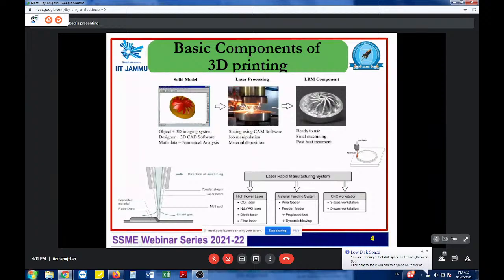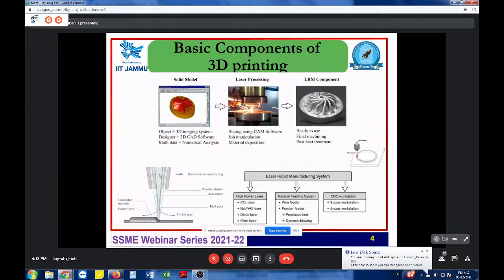The final ready-made product is obtained. Looking at the sectional view of this 3D printing technology — also known as Direct Energy Deposition (DED) — there is a coaxial feed in the nozzle with powders filled at 45 degrees, and at the center you have a high-power fiber pulsed laser used for melting. As the chart source shows, this laser-based rapid manufacturing system uses CO2, Nd:YAG, diode, and fiber lasers — the commonly used sources for 3D printing and layer-by-layer deposition.